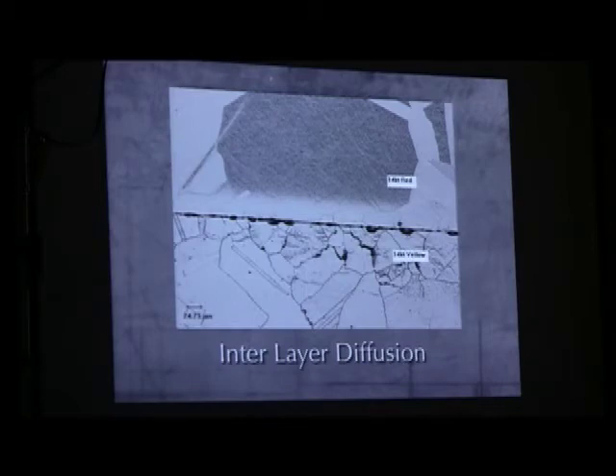So this is a micrograph of a lamination that I did that is 14 karat red, 14 karat yellow. The area that you can see that looks like somebody airbrushed at the lower limit of the 14 karat red is actually the diffusion of some of the elements in the 14 karat yellow into the 14 karat red. The dark line across the middle is actually an etching artifact from the preparation of this.